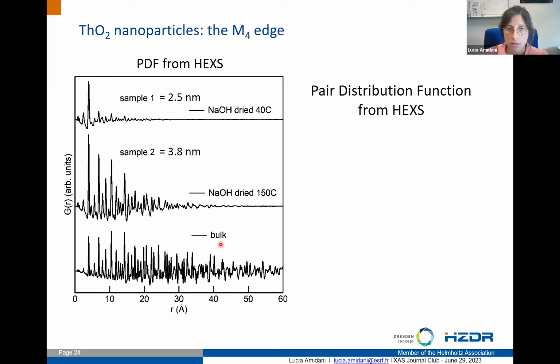You see here the bulk. If I measure a bulk, I get peaks up to long range, more than 6 nanometers and over. Here I have 3.8 nanometer nanoparticles from XRD, estimated from XRD.